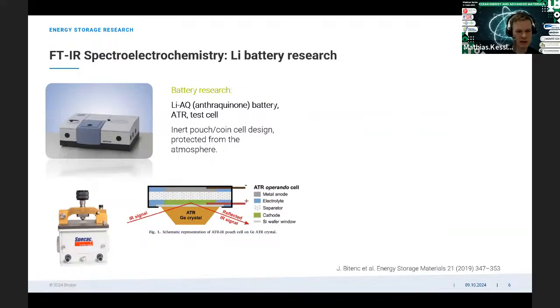The first application example I want to present is an example from the battery research. We have here a lithium battery test setup, and this is with an organic redox pair in the solution. And therefore, the coin cell is placed directly on top of an ATR unit, and this unit is installed in the sample compartment of the FTIR spectrometer. And then on top of the crystal, we have a window and then the cathode, and we can then probe the cathode directly during the electrochemical reaction in the cell.